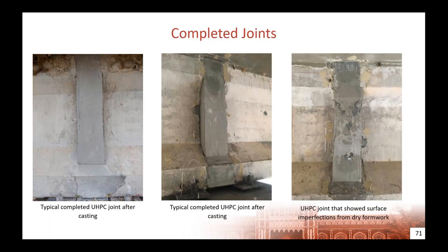And one of the great things about UHPC and the fluidity that it has, it allows it to fill up a lot of small, insignificant gaps that conventional concrete may not. So if you look at the left picture, you'll notice that some of the damage that was caused to the girder during the demolition, which is just part of demolition, was actually filled in by the UHPC because it was so fluid. It was a very small section, but it was able to cover up that portion of the concrete to add extra protection.